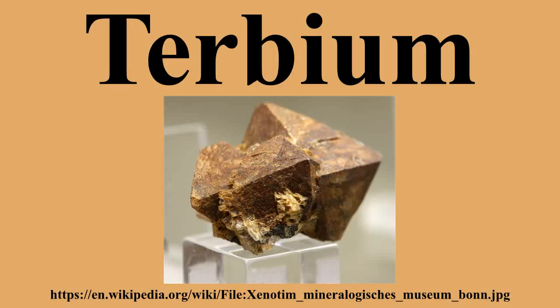As with other rare earths, terbium metal is produced by reducing the anhydrous chloride or fluoride with calcium metal. Calcium and tantalum impurities can be removed by vacuum remelting, distillation, amalgam formation or zone melting.